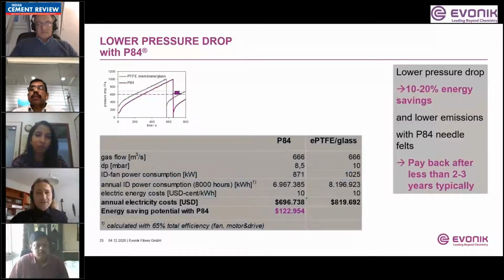So we did a calculation for 666 cubic meter per second. This is roughly 40,000 cubic meter per minute, equaling a baghouse in the size of 40,000 square meters, which roughly equals a 10,000 ton per day kiln. We can make this calculation also with your energy costs, your pressure drop experience, but with this difference, we could show the difference in energy costs is more than $100,000 per year, which is more than 10% of the bag costs per year. So the typical payback of P84 bags, even if a woven glass bag is performing very well for 2-3 years, is typically not more than 2-3 years. And for the rest of the life of P84 bags, you save more money and you can sleep well because you know that the bags will perform well.